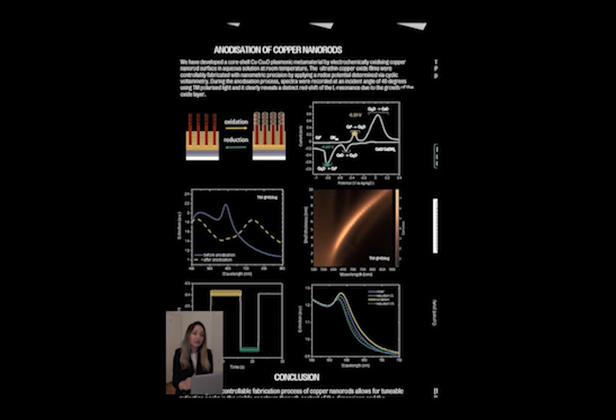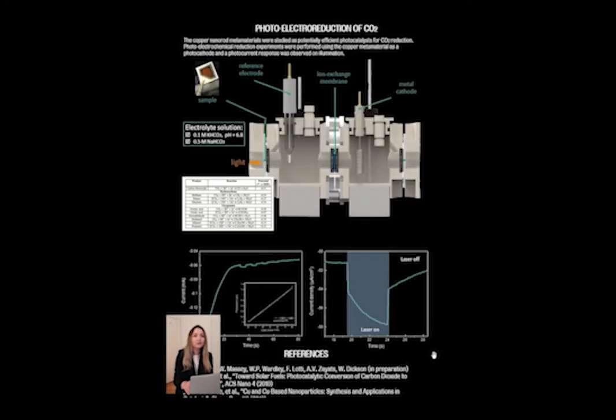An examination of this result clearly reveals a dramatic redshift of the L resonance in experiment but also in simulation due to the growth of the oxide layer. In addition, we also optically observed the reversibility of these processes. Furthermore, copper nanorods with a surface oxide layer can be used as catalysts for photoelectrochemical reduction of carbon dioxide.